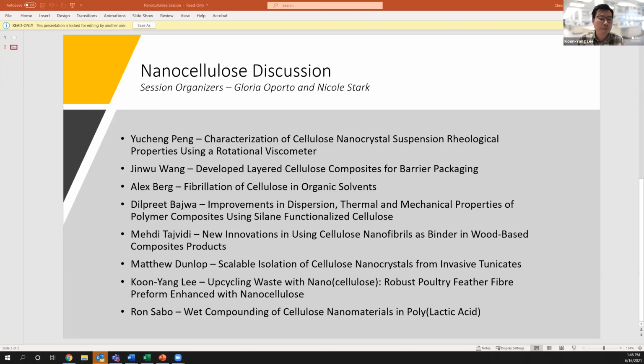Effectively, you get a bunch of loose fibers, whether it's chicken feather fiber or natural fibers or whatever it is. Typically, you need a polymer to bind them together. In our case, we actually use nanocellulose with its effect to form reversible hydrogen bonds together, and we use that effect to bind these loose fibers together. We are able to demonstrate in this particular presentation that the bending properties of these nanocellulose enhanced fiber board, if you will, it's stiff, it's rigid, and under the right condition, in the case of a chicken feather, you are able to deconstruct the whole thing, recover the chicken feathers again.